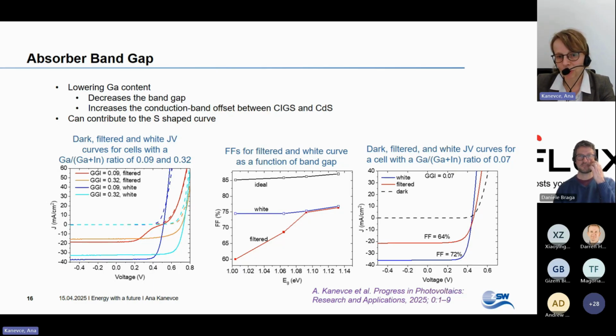So when one looks at the JV curves, this is not an S shape. This looks more like a series resistance, but it's significantly lower fill factor in the red, so for a filtered light, than for white light. And one can really do JVT measurement at lower temperature. This curve is not a series resistance anymore. One can see a very well pronounced kink.